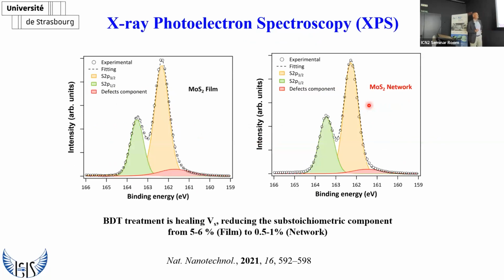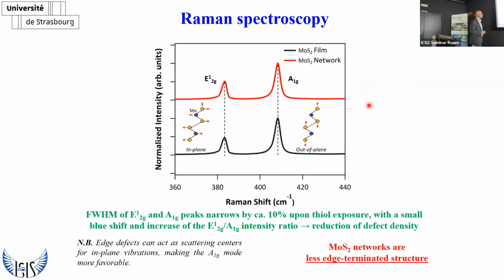Now, how can we prove that this kind of network has been formed? We can look at the Raman and at the XPS spectra. In the XPS spectra, we look at this substoichiometric component in the film, and the intensity of this substoichiometric component reduced from 5 to 0.5% upon network formation, demonstrating that we have a decrease in the defectiveness within the film. Likewise, we also performed Raman spectroscopy. This was done by Andrea Ferrari in Cambridge.